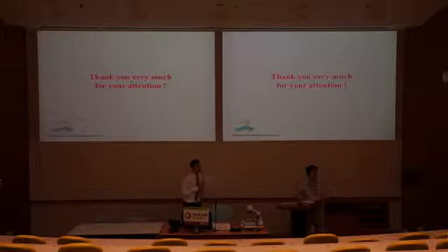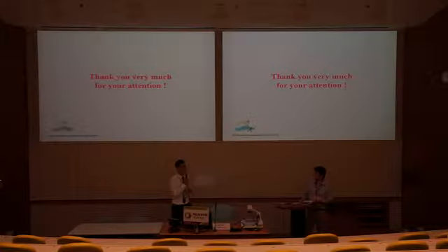Yeah, sure. I used the LAMMPS package to do the MD simulation. So what kind of potentials do you use? The DREIDING potential, because it is really suitable for our molecules and this system of supermolecules and polymers. So how about the graphene inside? Graphene? Well, we also use the DREIDING potential. Good, thank you.